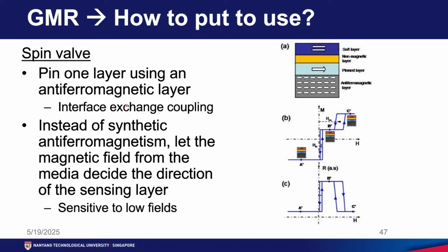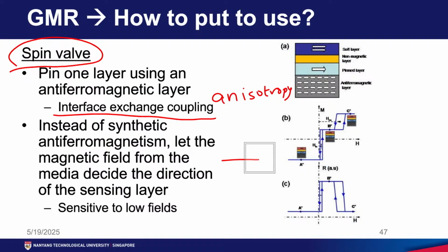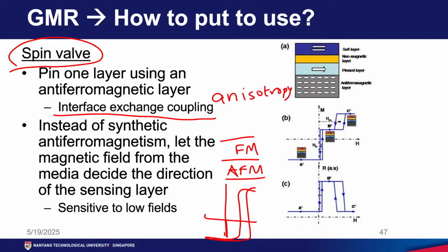Then the three people that I showed you earlier, they came up with a concept called spin valve, which uses some of the things that we discussed earlier. So, we discussed interface anisotropy earlier. So, I told you that when you have an antiferromagnetic layer in the vicinity of a ferromagnetic layer, then you can have the hysteresis loop shifted in one particular direction. Okay. So, this one we learned briefly. So, this group of people used this concept of exchange bias to fix the magnetization direction of one of the ferromagnetic layers.